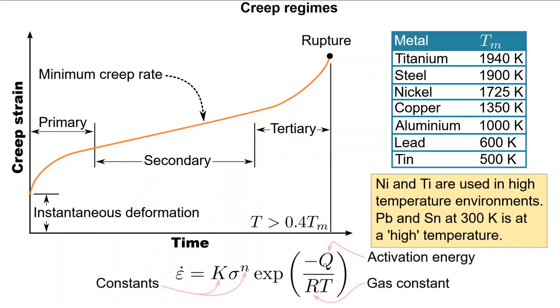I'll get into why in a minute, but for a representative creep test, we can come up with an empirical relationship which describes the minimum creep rate. Like we have seen previously regarding other elevated temperature phenomena such as diffusion, the creep rate is captured with an expression that looks like this. Here, Q, K, and N are coefficients which describe the material system. Both higher temperatures and stresses will exponentially increase the creep rate.